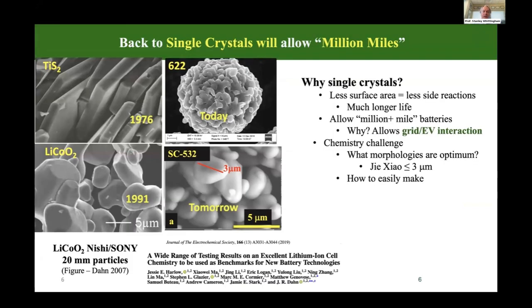So let's just look at this single crystal issue. And I expect Jeff talked about that earlier today. If we go all the way back to day one in the 1970s, when we built the first lithium-ion batteries, we used titanium disulfide, very large single crystals. These were probably 100 microns thick and up to 1 centimeter in length. So very, very large. It reduced the reactivity with the environment, but also we could do that because TiS2 is essentially a metallic conductor. So we have no difficulty in getting electrons in and out. And that higher metallic conductivity also allows the lithium ions to move very fast.